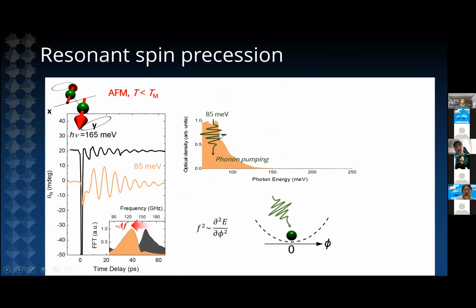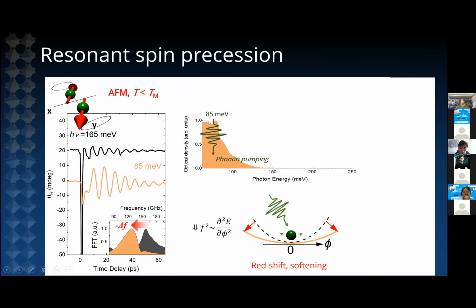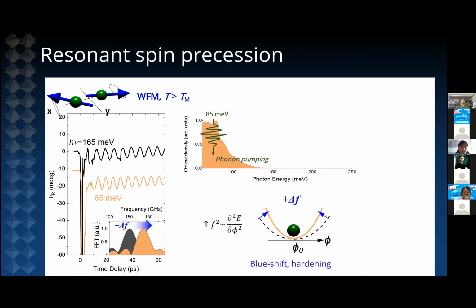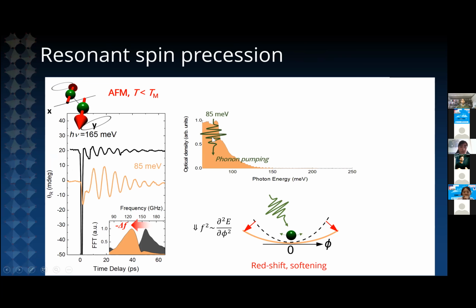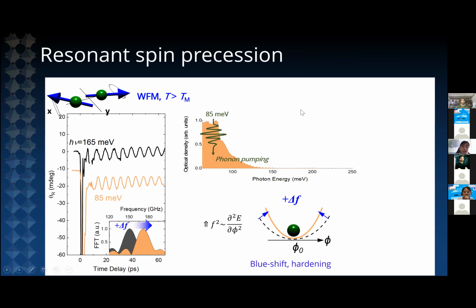But now, if we excite the system in resonance with a phonon mode, the spin precession is indeed activated with a larger amplitude, but the frequency of the spin precession itself is being changed. So we see a very large redshift of the magnon frequencies in this system. So this directly indicates that by exciting the lattice modes, we are changing the magnetic anisotropy. If we do the same experiment, so this is measured in the low temperature antiferromagnetic phase. In the high temperature weakly ferromagnetic phase, we also observe a modulation of the magnetic potential, a change in magnetic anisotropy, through a blue shift of the magnon frequencies.